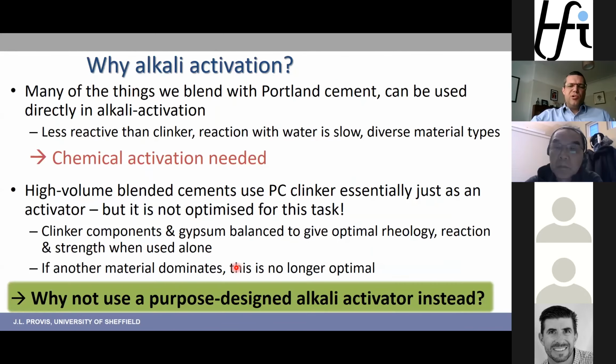So I talk a lot about alkali activation, and this is one of the classes of innovative cement that we look at. One of the big classes that we look at is alkali activated cements. It starts from the starting point of, we've got these high volume, widely understood, widely recognized mineral powders that we blend with Portland cement, that we call supplementary cementitious materials. And if we would just mix these with water, they react a bit too slowly to be useful.